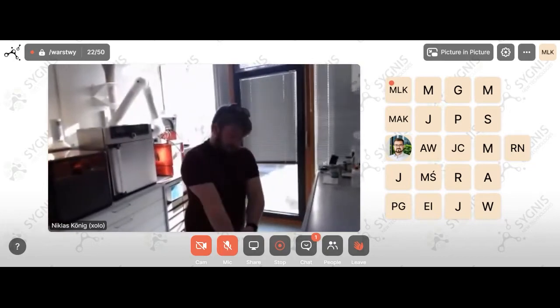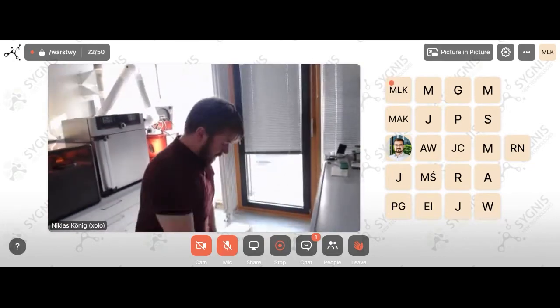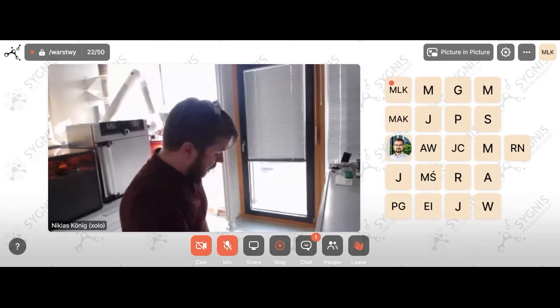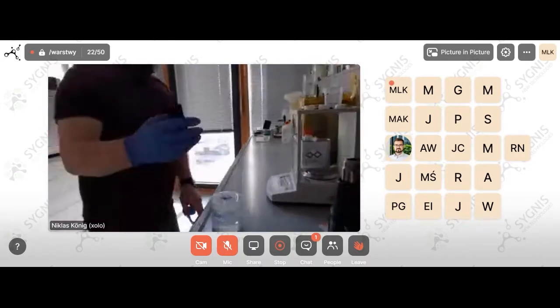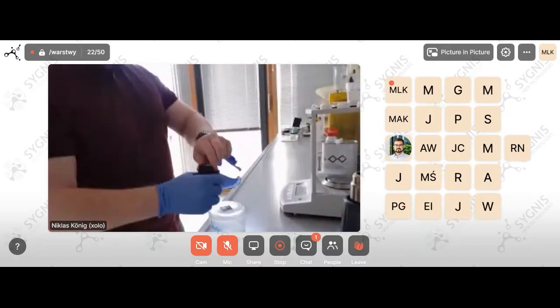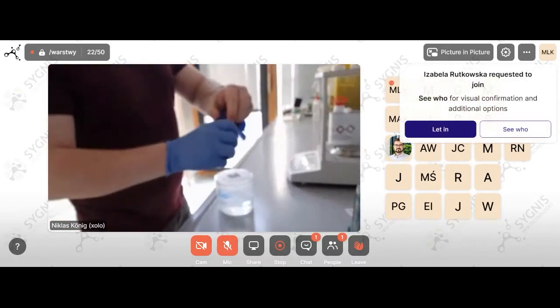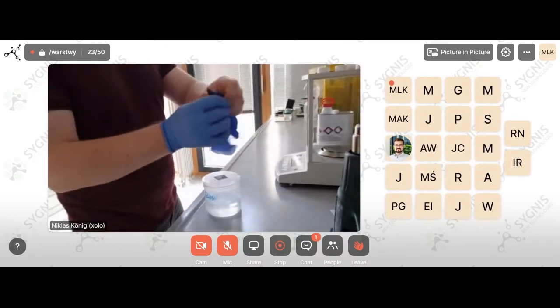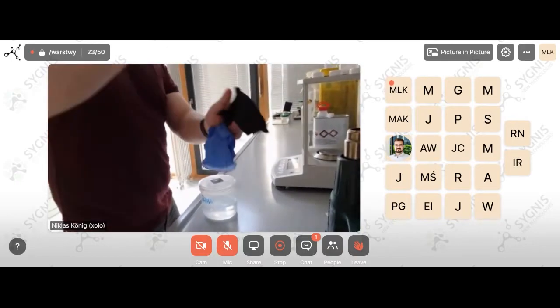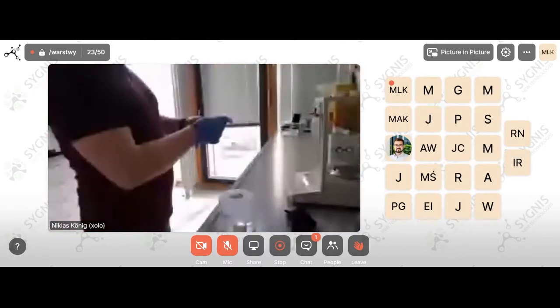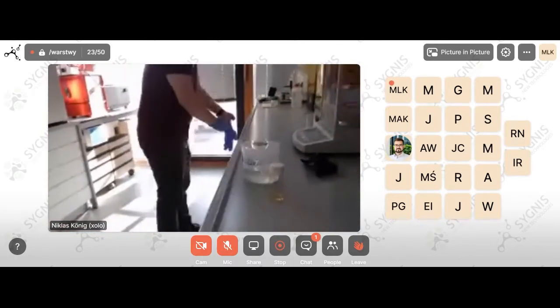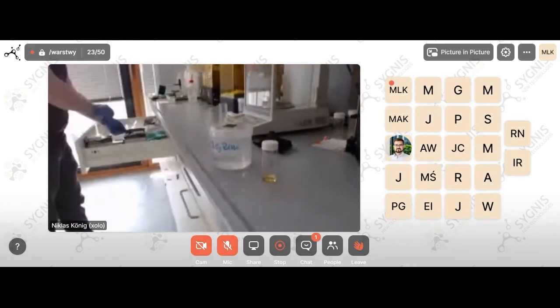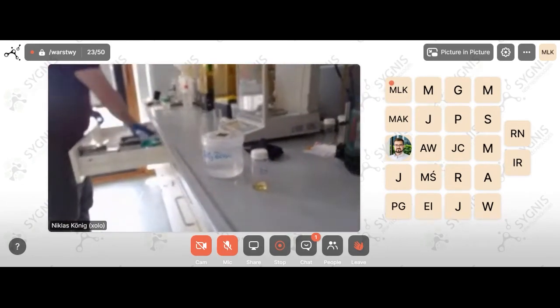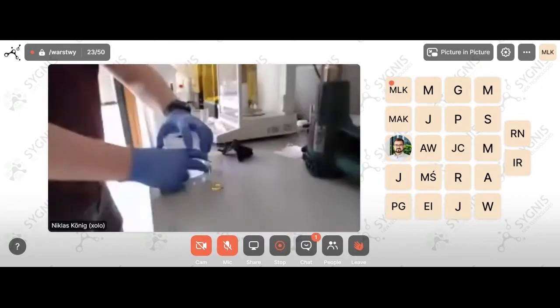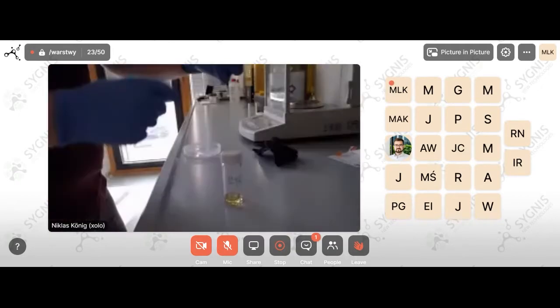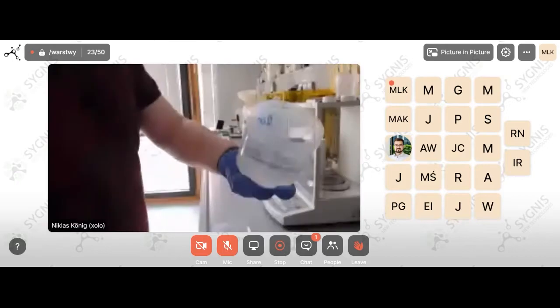Okay, and now we make the resin preparation. Here we use a urethane methacrylate. It's 200 grams. And here is our photo initiator, dissolved with a co-initiator. Now we mix these two liquids. And here you can see the high viscosity of our resin.